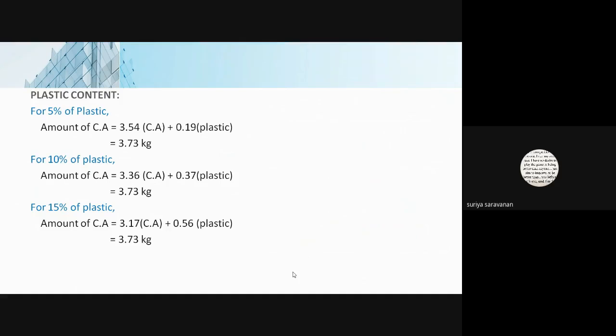So for the coarse aggregate, we replace it with 5% plastic aggregate, 10% plastic aggregate and 15% plastic aggregate in the coarse aggregate. So this is what we have obtained here. The total will be 3.73 kg. In that, we have taken 1.5 parts of coarse aggregate divided by the total of 3.25 parts, into the weight of 1 cube, which is 8.1. Accordingly, we have got these values for plastic content.